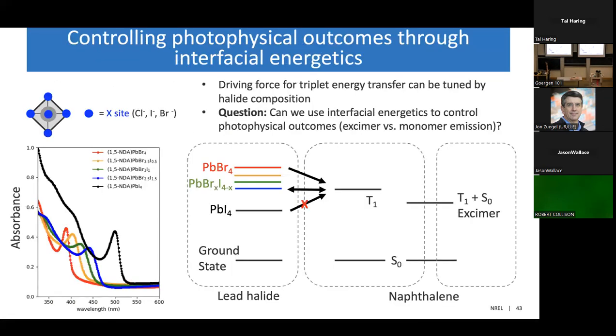And when we look at the perovskite PL in this figure, clearly the spectra is more excimeric. So because of this, we had a question of whether we can control photophysical outcomes in these materials through interfacial energetics. So one of the things people love about these hybrid perovskites so much is how tunable their optical properties are. So we can mix the halide site in these perovskites from chloride to iodide to bromide to get really nice transitions in their exciton energies.